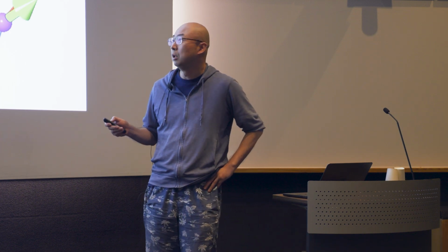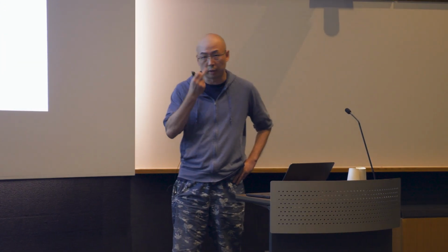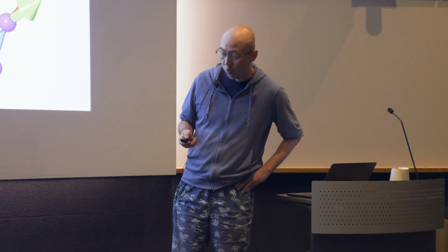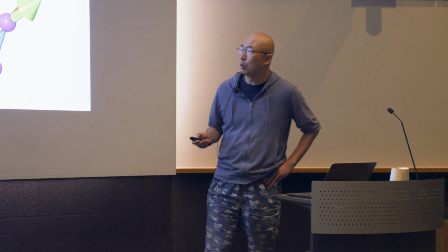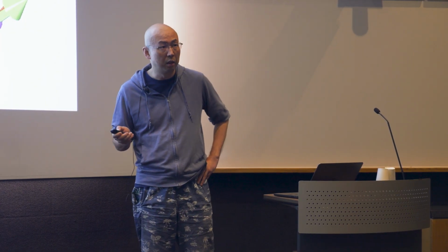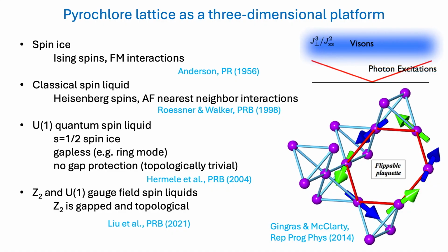The reason I pick pyrochlore lattice is mainly because these 3-dimensional materials are much easier to handle during preparation and measurement. And you can get to much higher quality with that. Of course, Anderson already designed the spin ice on this set of lattices. And then you also can have a classical spin liquid by having the antiferromagnetic nearest neighbor interaction of the Heisenberg spins.